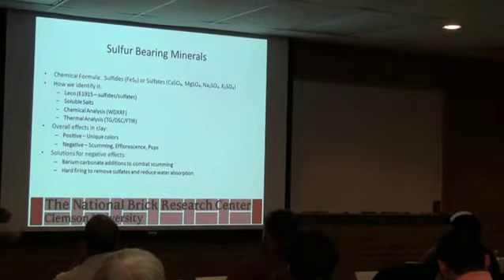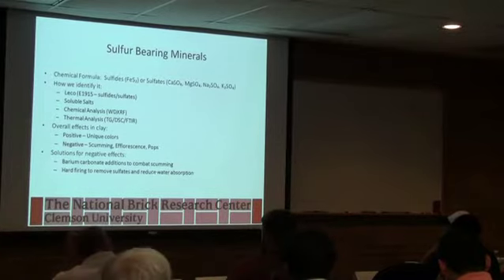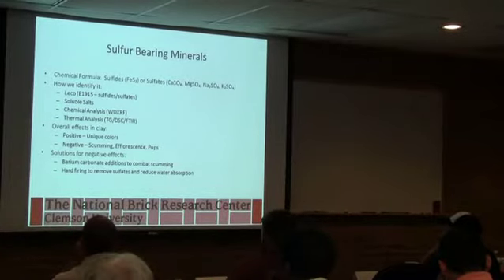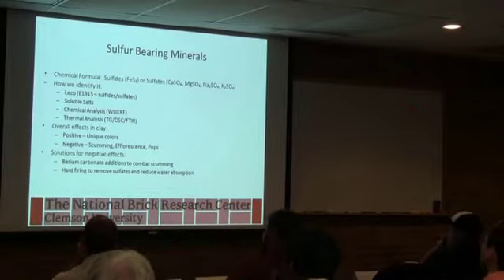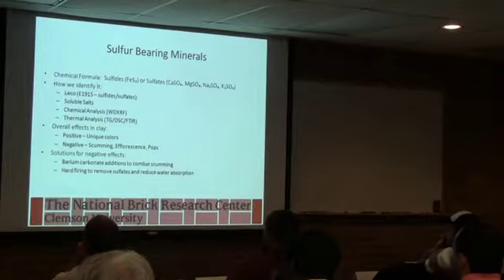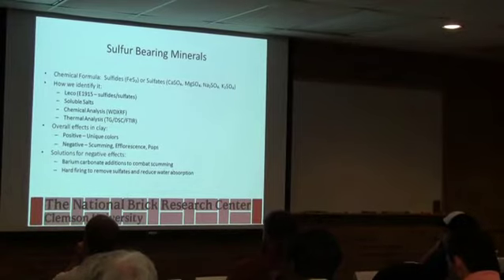So if sulfur is a problem in the fired brick, your best bet is to get it out, if at all possible. The only way to get it out is higher temperature and longer time at high temperature, which also tends to reduce water absorption. So since these things are soluble, you're helping yourself in two ways there. One, you're lowering the sulfate content, and two, you're making it harder for water to get in and find that soluble salt and bring it back out. So it's sort of a combined thing.